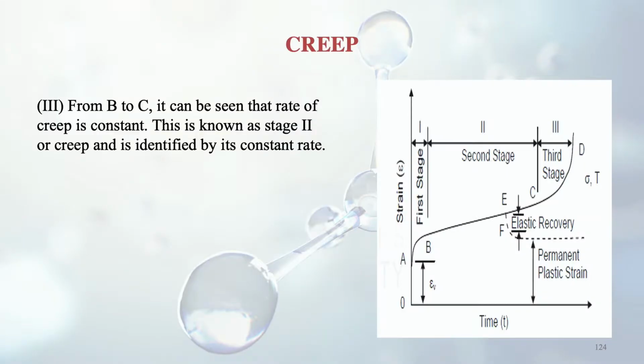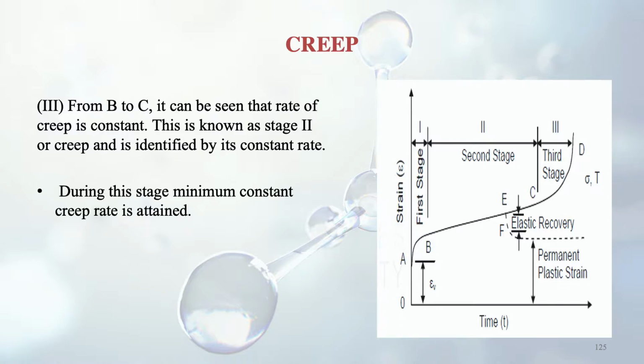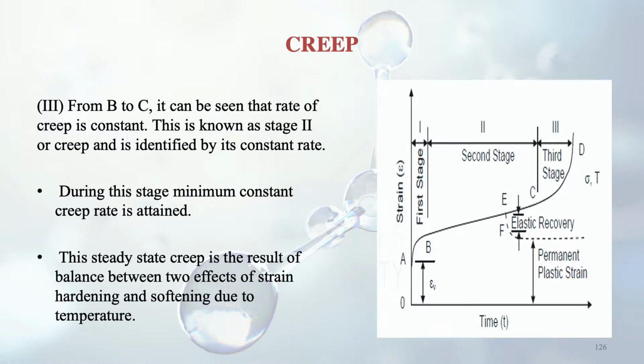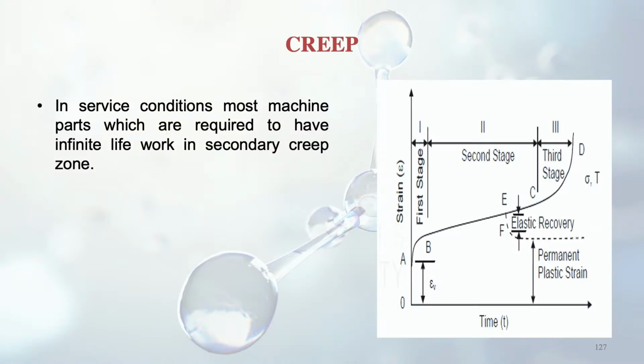From B to C, it can be seen that the rate of creep is constant. As I told earlier, the slope of the line is constant, and so it is a linear one. This is known as stage 2 creep, and is identified by its constant rate. During this stage, minimum constant creep rate is attained. This steady state creep is the result of a balance between two effects. So why is it happening like this? Now we are understanding. There are two effects. One is the strain hardening, and the other one is the softening due to temperature. In the earlier case, from A to B, only strain hardening was taking place, whereas in this case, strain hardening is taking place, but it is being compensated by the softening due to the temperature. In service conditions, most machine parts which are required to have infinite life work in the secondary creep zone.